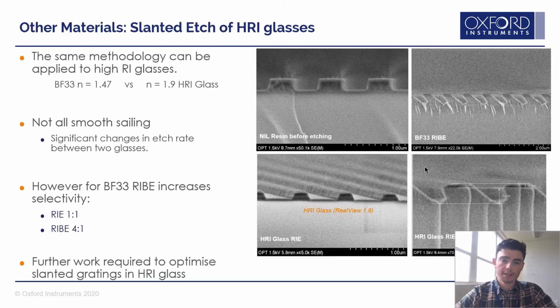This can also be applied to high RI glasses. So here we can see a comparison of a standard glass to an N1.9 glass, something that would give us an improved field of view compared to the current resins. And you can see in the far right hand side, we've managed to mimic the behavior in the standard glass in the high RI glass. Of course, there are some hiccups. Changes in the structure of the glass and how it behaves means that we get changes in things like etch rate. It's not quite as easy to get that perfect grating that we're looking for. But we still benefit from the improvements in the selectivity. So it's an exciting avenue of progress that's still ongoing.